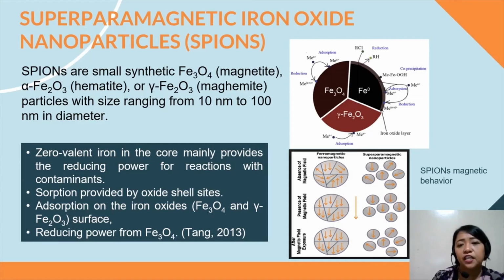Okay, as you can see here in the picture on the right, this is a representation of your SPION. We have zero valent iron in the core, mainly providing the reducing power for reaction with contaminants. We have an oxide shell which provides sites for sorption, and adsorption happens on the iron oxide surface while the magnetite possesses reducing power.